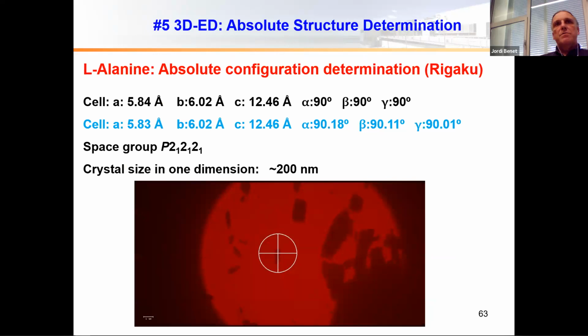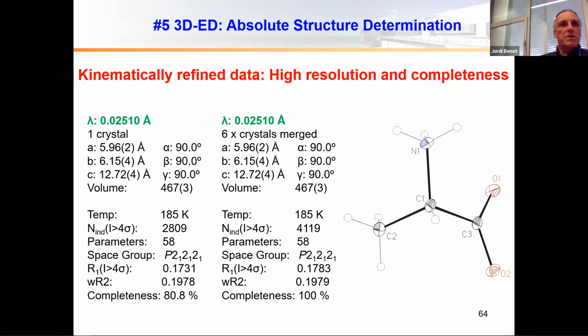So one first point then is we determine the unit cell and check how precise our unit cell determination was, and we were really surprised. One of the points which some people make is that the angles and values of the unit cell are not so precise using this method, but it seems to be quite well corrected and seems to be working very well. And so we could also easily find the space group, which is quite a common space group, and we got the results.